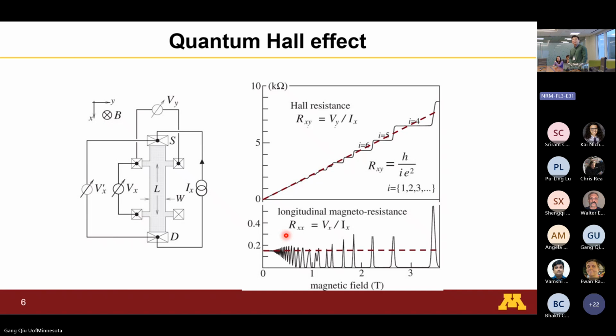Right, so what happens if you have a very thin layer of material, and it's extremely clean without all these scatterings? Now, when you do this measurement, you will see that the Hall resistance is no longer a line. It develops into these discrete plateaus or steps, right? And these are not some random steps, right?